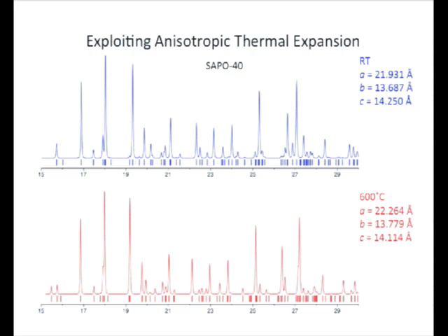And now look here. Here we have three reflections. Two of them are overlapping here. Here, they're separated. Simply because the lattice parameters have changed a little bit, the overlap pattern has changed. And so now we know that the two reflections under here are actually about equal intensities.